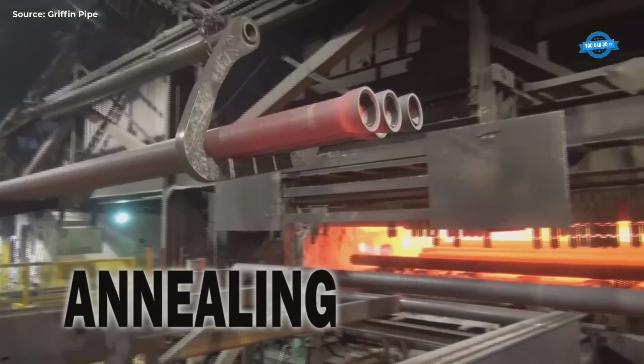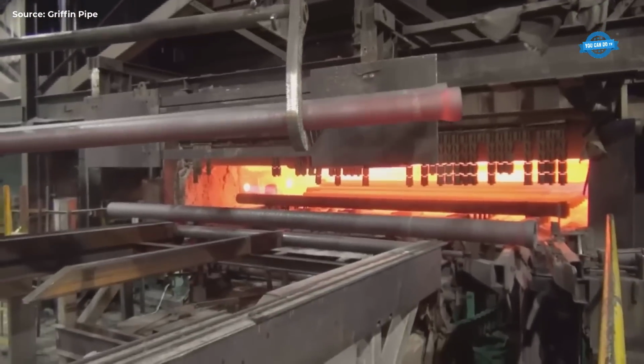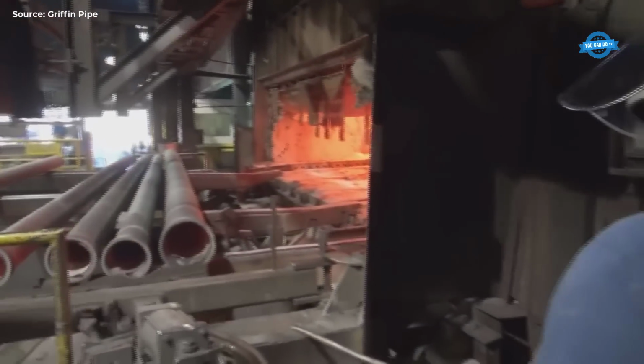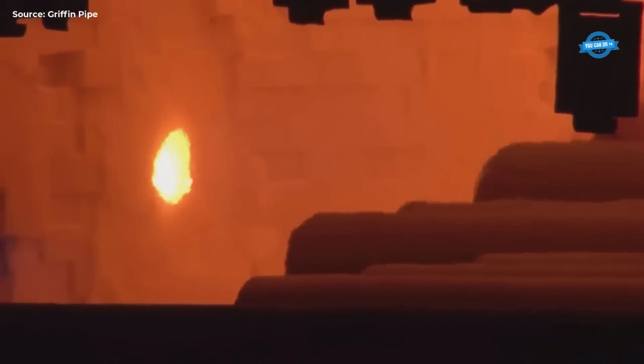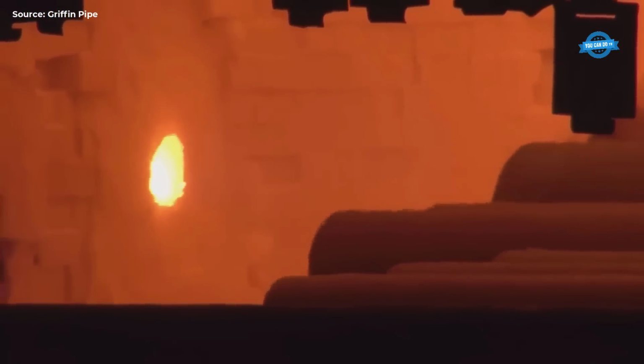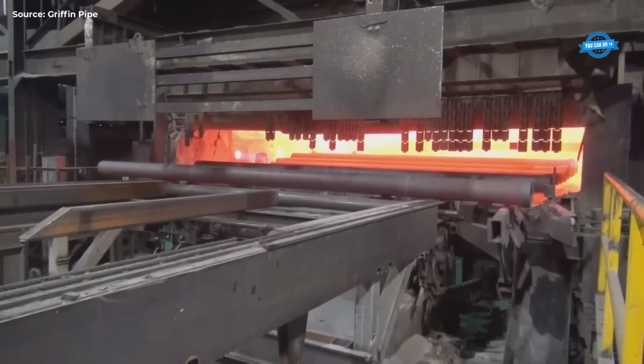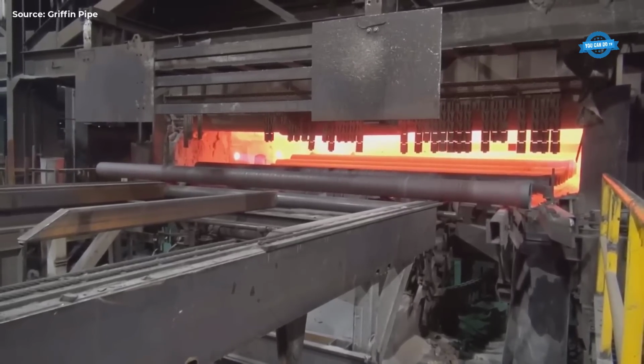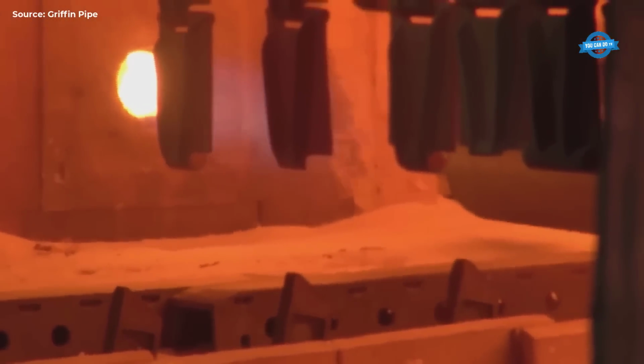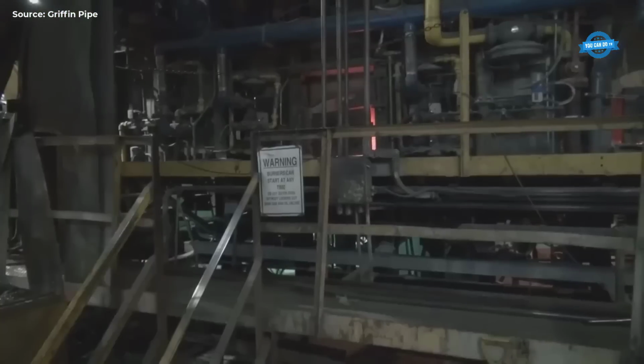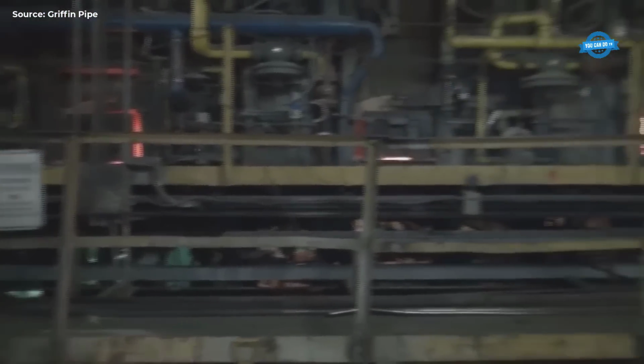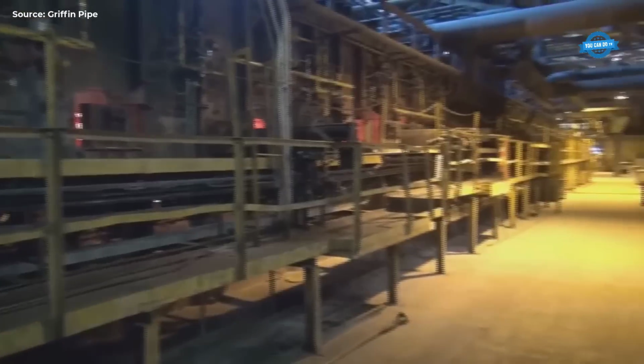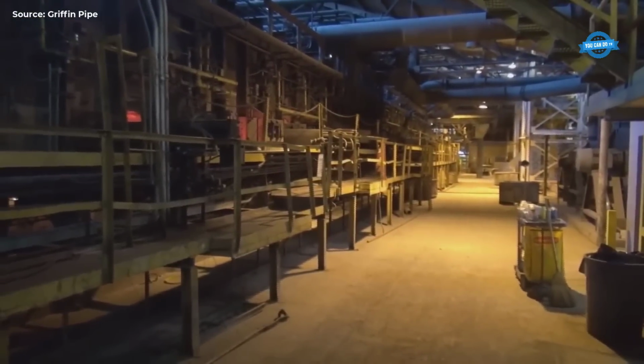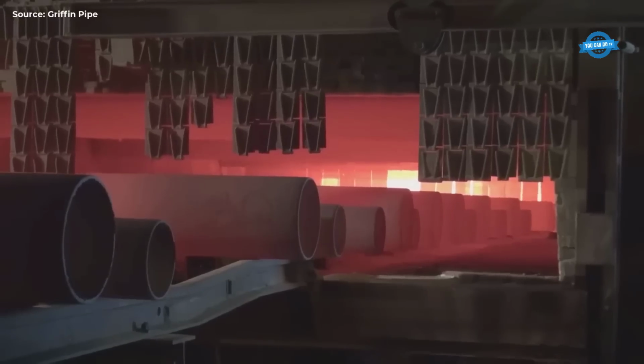Annealing. The hot pipe is placed on rotating rollers to maintain roundness and straightness before being placed in the annealing oven. Annealing is a heat treatment process that produces the desired mechanical properties of the ductile iron pipe. This takes place in a natural gas-fired oven where the temperature gradually decreases as the pipe moves through the oven. The annealing cycle takes about 35 to 45 minutes. Prior to annealing, the pipe is fairly brittle due to rapid cooling during casting. The annealing process ensures the pipe has the correct properties and does not crack easily.